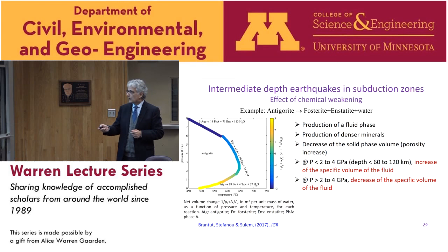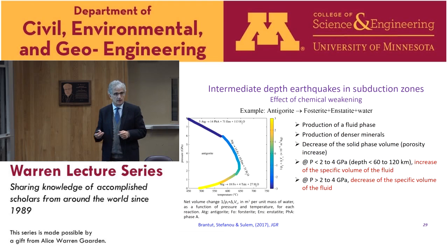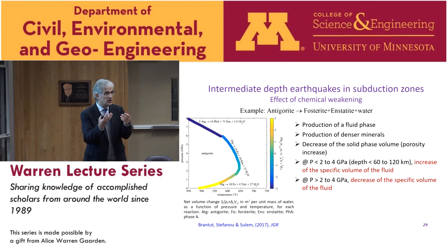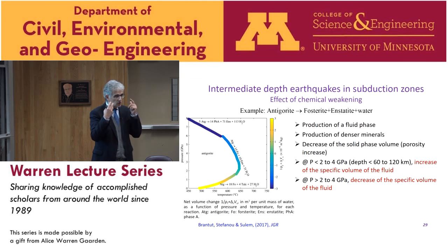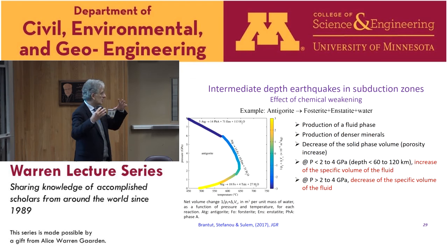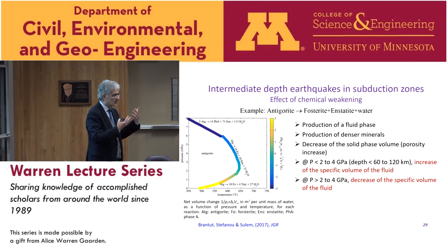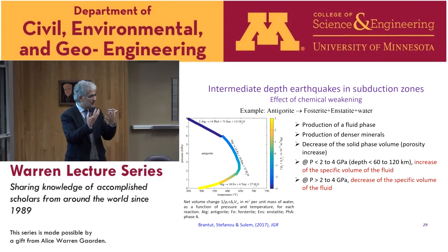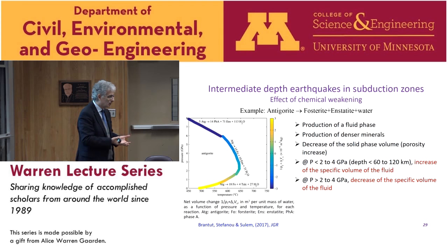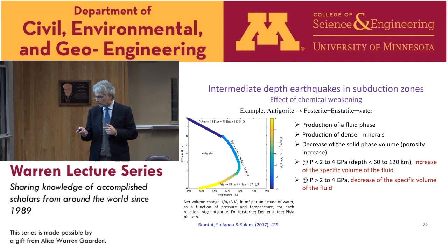But if the pressure is higher, so at even higher depth, we have actually a decrease of the specific volume of the fluid. So in that case, we have actually a decrease of the pore pressure because the creation of porosity is such that the pore pressure is decreasing. So if the pore pressure is decreasing, it means that we have an increase of the effective stress. Now imagine the analogy with a porous rock, for example, a carbonate or chalk, very porous, under a very high confining pressure, we know that we have the phenomenon of pore collapse. So this is what actually occurs here.